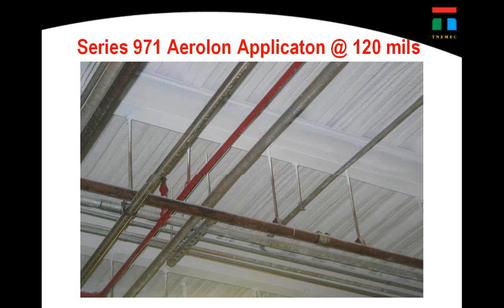The Aerolon technology basically is slowing the transfer, and I'll show you that shortly, slowing the transfer of temperature so it never reaches dew point. So if we can slow down the temperature change from cold or hot to a surface, that's why you can put your hand on this material up to 400 degrees F at basically 60 mils, or 1/16 of an inch thickness, without burning yourself. That thermal transfer is happening so slowly that you never reach temperature. In this particular case, you never reach dew.